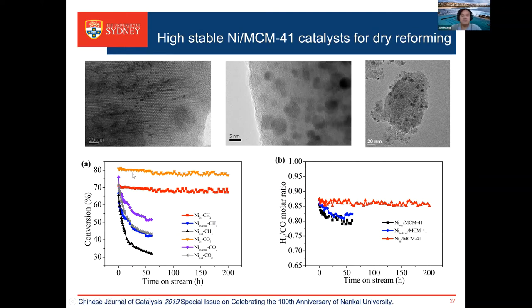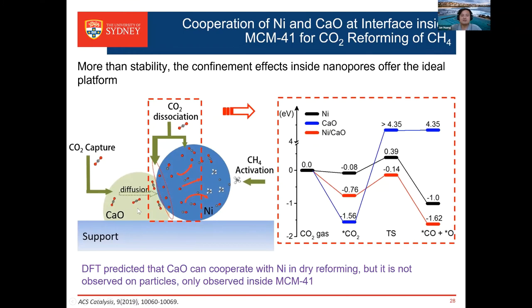And we found that if it is totally inside the pore, it keeps a higher conversion and never loses activity. But if it is a mixture or totally outside the pore, the activity is lost, as in most current published results and even in industry catalysts. Later we introduced calcium oxide inside, combining carbon capture and reaction together. We can put this device in the exhaust gas system, capture and convert it to important fuels.